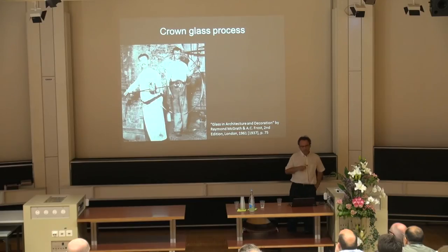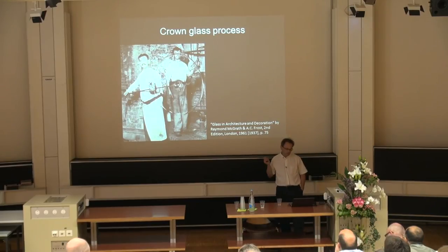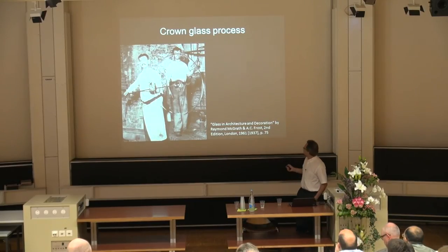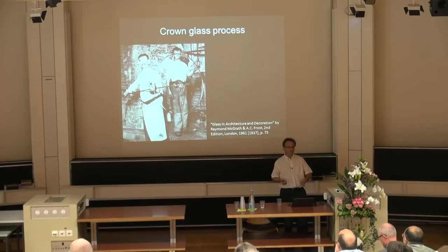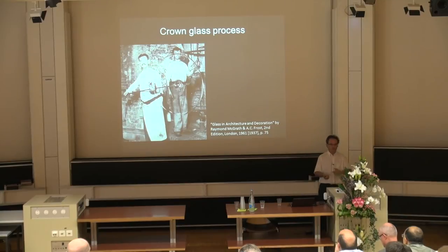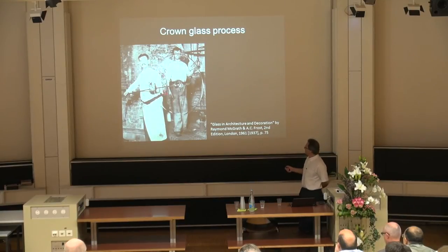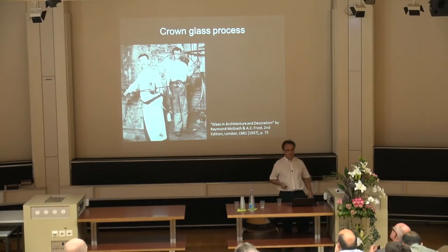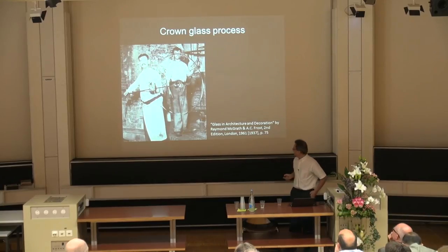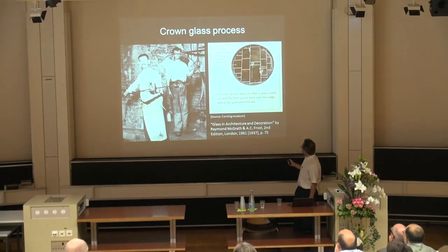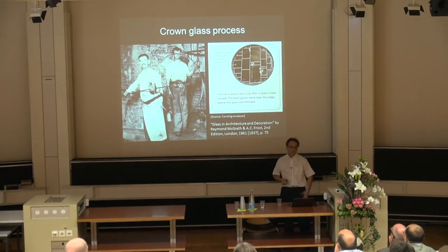It's the way people were making glass at that time, and still this is used, it's called the crown glass process, where maybe you have seen glass makers doing that. You spin this disc of glass, increasing the speed, and use the centrifugal force to pull the glass out and form that disc. And then what you do after is cut pieces out of that. But of course, this is not homogeneous in thickness. Okay, it's very hard to get a perfectly flat one.